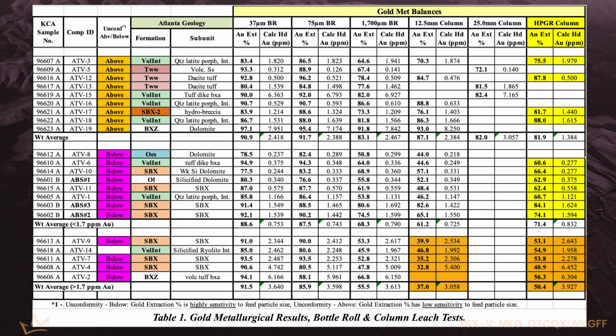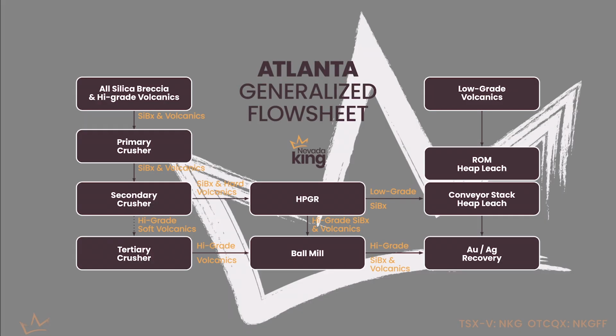So as the grade drops in the silica breccia, the recovery via conventional or HPGR crushing improves over the high grade, and you actually get a very favorable response of the silica breccias at somewhere at 1.5 grams or less. We achieved a 71% column leach recovery on an HPGR product from the silica breccias. So we certainly found out during this phase of test work that the high grade silica breccias need to go through a mill, and the low grade needs to go through HPGR crushing and then go into a conveyor stack heap leach. Going forward, obviously, we need more variability samples and testing to cover a broader range of both silica breccias and volcanics so we can continue to develop the flow sheet and optimize the conditions for how this project should run.